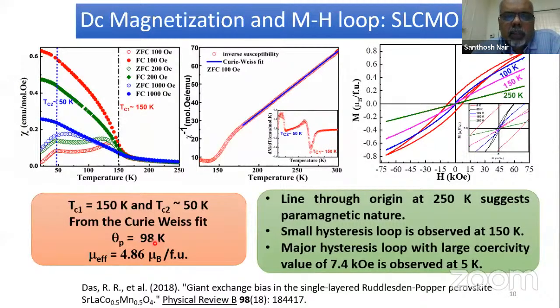Okay. Now we look at the magnetism. So you see around 150 K, we get an upturn in the field-cooled magnetization as well. The parent ferromagnetism is somehow still present there, but it's not as strong. But you see at the lower temperature, at 50 Kelvin, there is another feature. So what is this feature about? Conventionally, we look at the paramagnetic region and do a Curie-Weiss fit to understand what is the spin state of the magnetic metal ions.